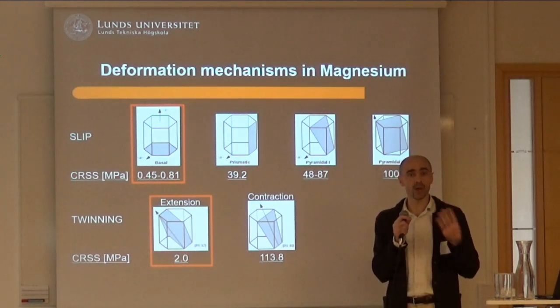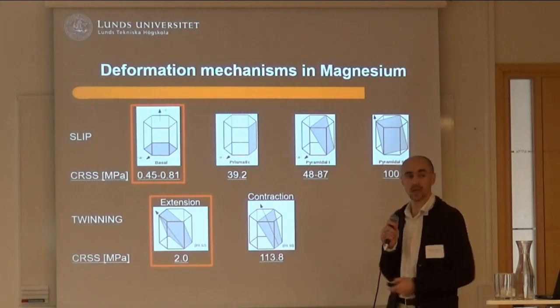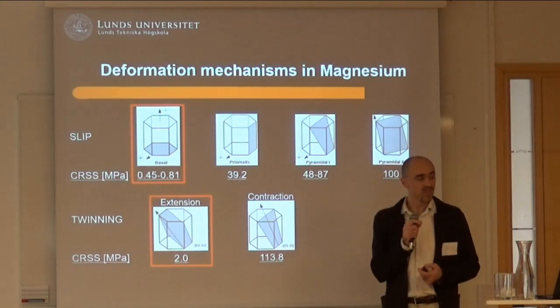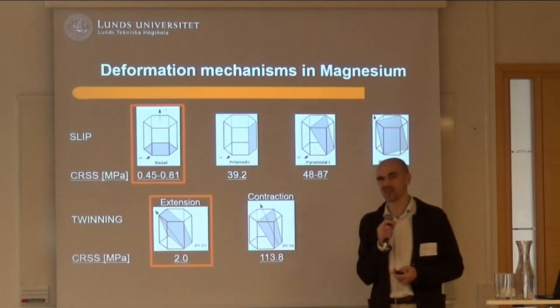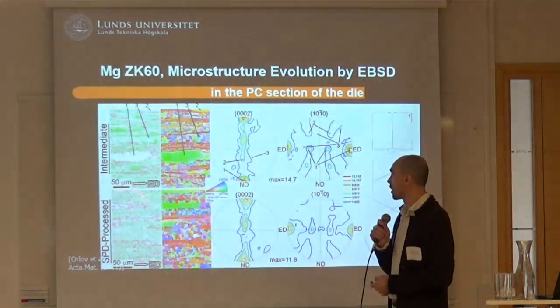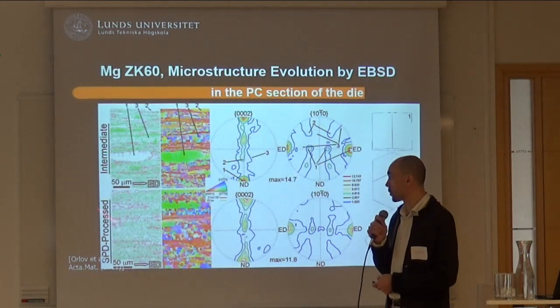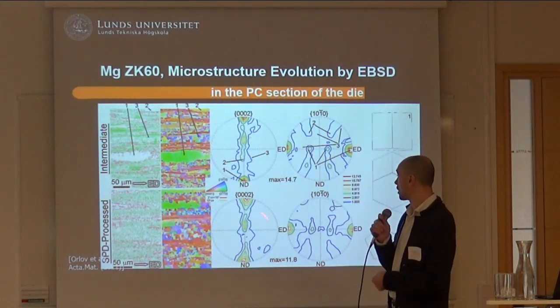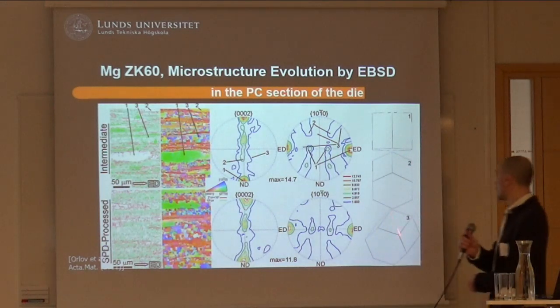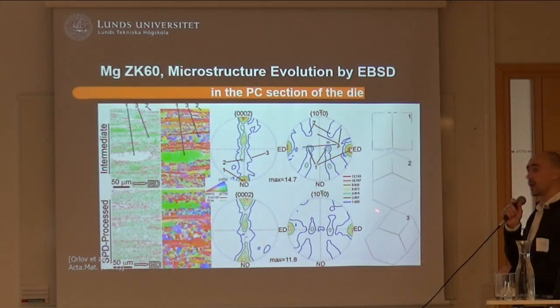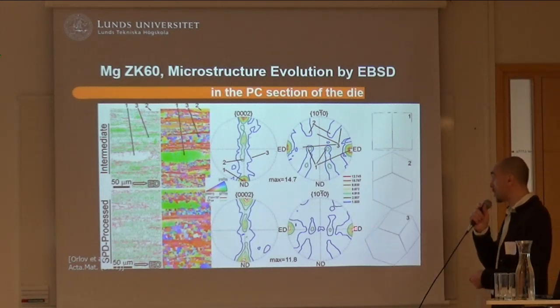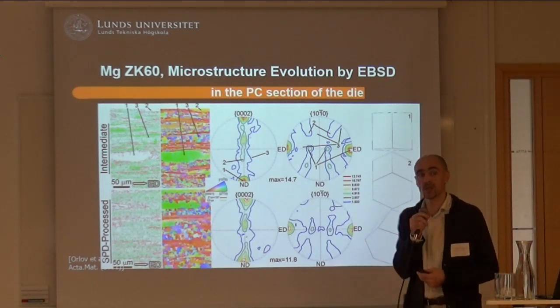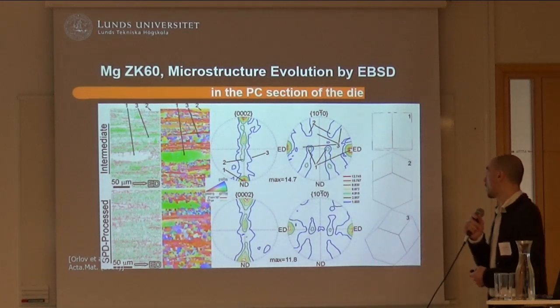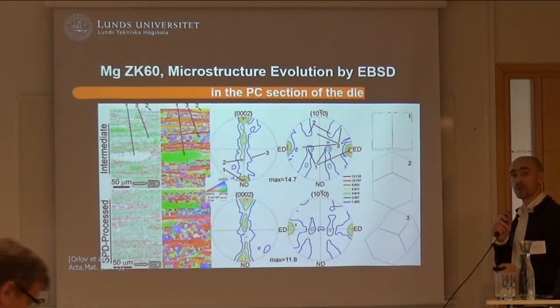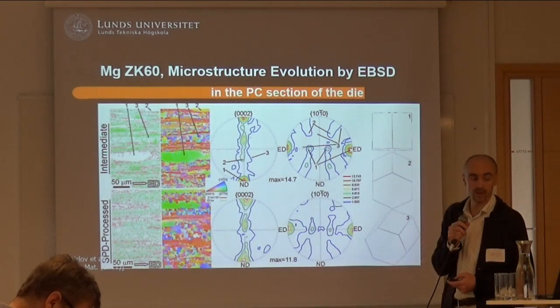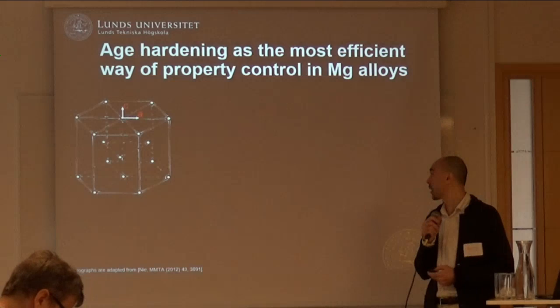This can be achieved by controlling the orientation of these blocks and controlling the slip itself by some precipitation hardening. A couple of slides on that. In the material which we processed, we call it SPD processing, right? What we've done here, these 4 figures, they show orientation of unit cells of magnesium. We randomize the microstructure of the magnesium alloy, and by that we activate multiple deformation mechanisms in it, which improves the strength of the material and its isotropy.